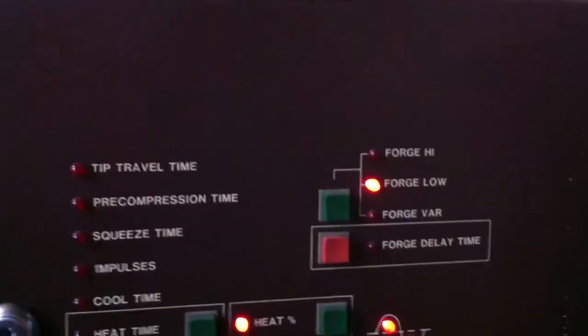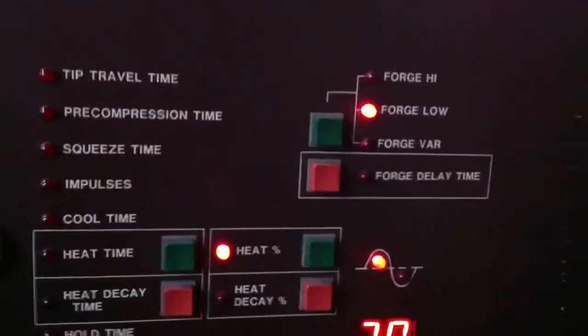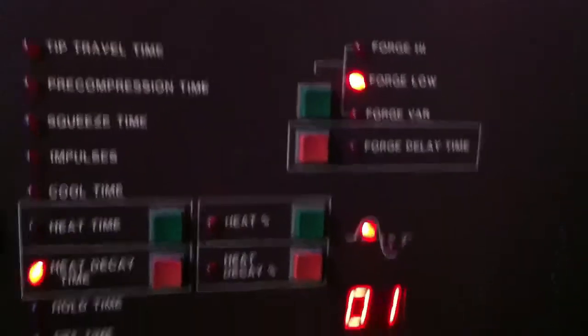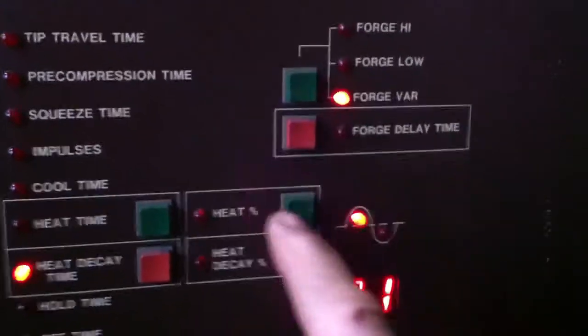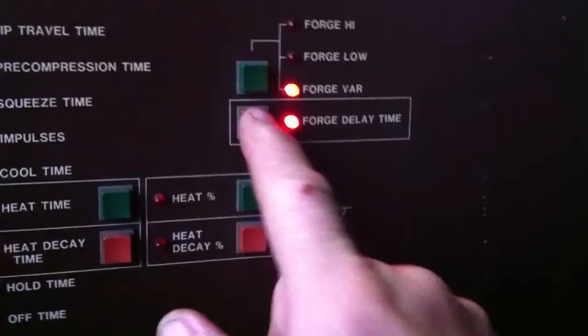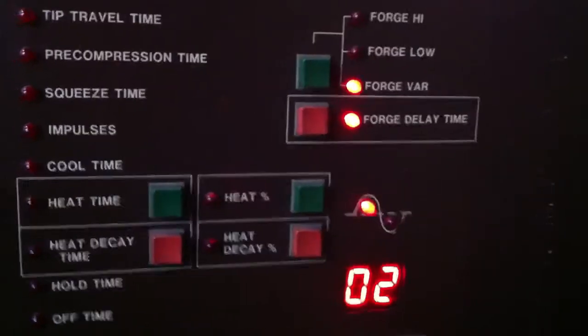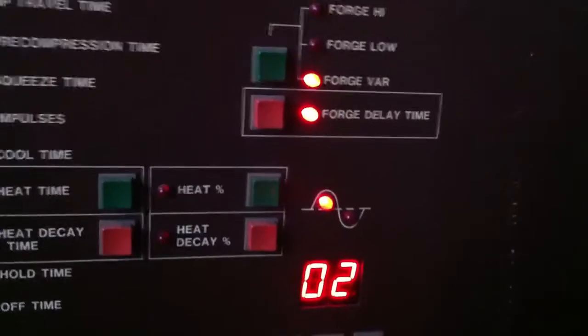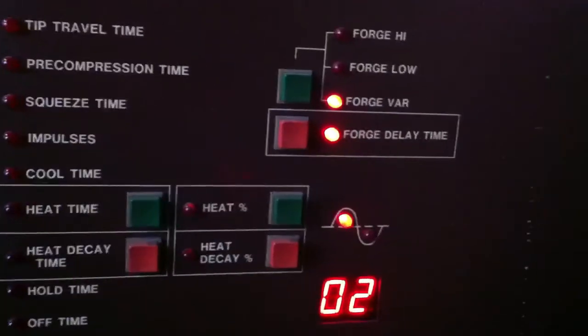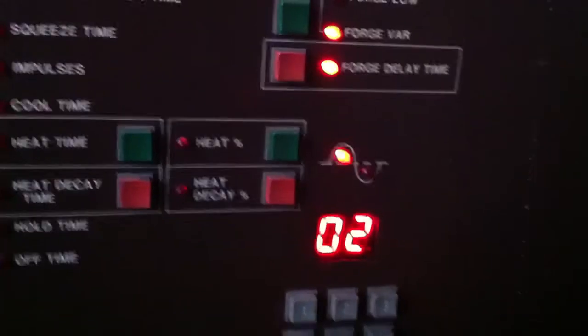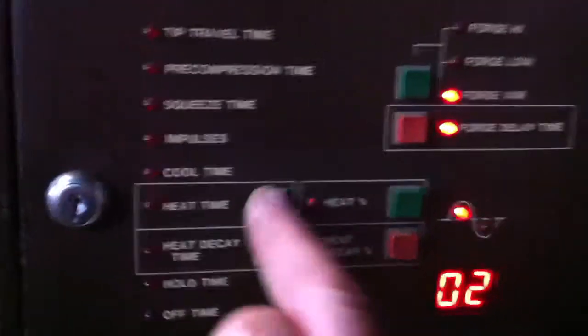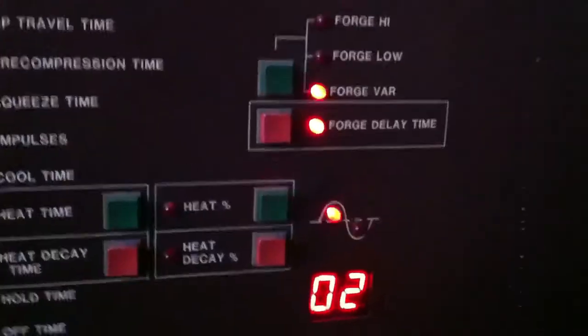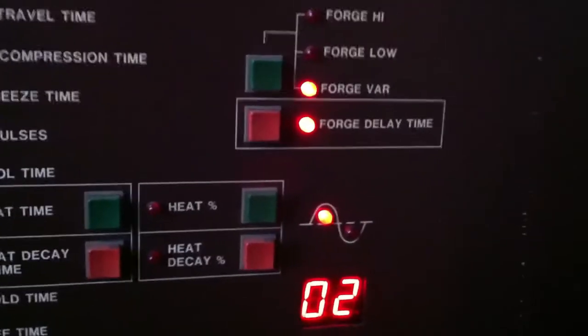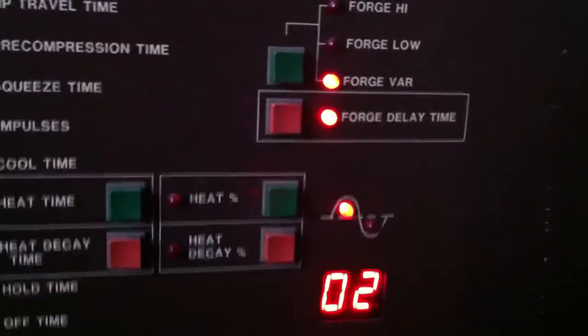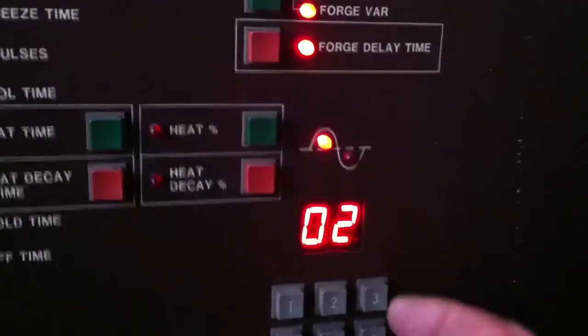The forge, that comes into effect in the middle of your weld. If you have forge delay on there, or forge variable, and you put in a forge delay, what will happen is it will drop out the buck pressure on the bottom of your cylinder so you get the full force of the weld, and you put it in the middle of your weld typically so you don't crack welds. So if you have 16 cycles of weld time, you would want your forge delay to be 8 cycles. So at 8 cycles your forge will drop out and all the pressure of the head will be on your tips. And typically that's for aluminum welding.